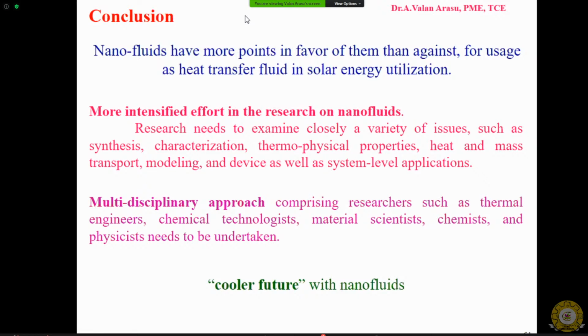So we have to do a lot of research before we use this nanofluid in any particular application. We can use any nanoparticle, as I said. We use solid nanoparticles because they have higher thermal conductivity. The effective thermal conductivity of the nanofluid is going to be higher compared to any other metal oxide. Or if you use some carbon-based nanofluids, because the thermal conductivity of graphene or carbon nanotubes is a few thousand, they are much higher than even metals. So the effective thermal conductivity enhancement could sometimes be even 200% more than the thermal conductivity of the conventional fluid. So it depends on the application and more intensified research to choose a particular nanofluid or nanomaterial.